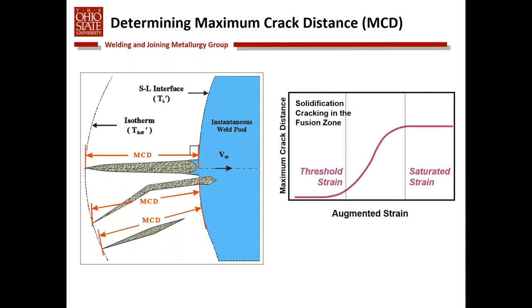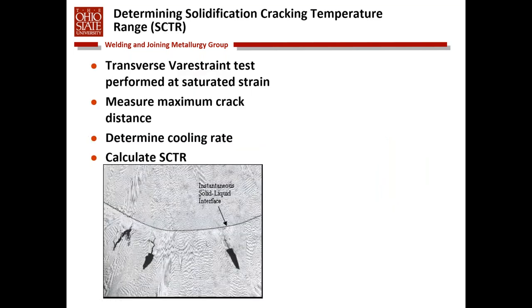The data that is generated from the Varestraint tests often looks something like this in terms of maximum crack distance, where at low strains, there is no cracking. You reach some threshold strain where cracking is initiated, and then at higher strains, you basically level out. And so we can either use threshold strain or this maximum crack distance at saturated strain to quantify the cracking susceptibility. So this is an example of what cracking might look like at the trailing edge of the weld pool. This is a plan view, so we're looking down on the surface of the weld, the instantaneous solid liquid interface.